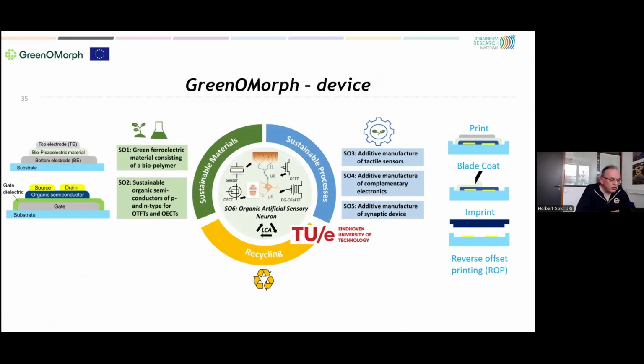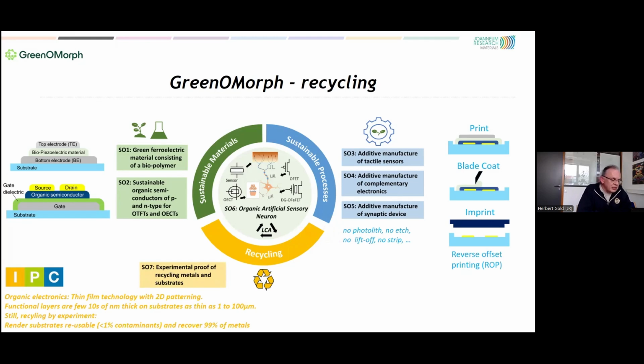So we would create a neuromorphic device by using sustainable materials and additive processes. And it's a layered technology, so we have only tens of nanometers thin layers, and we have substrates which can be as thin as 1 micrometer, but a maximum 100 micrometers thick. Still, we want to demonstrate experimentally that we can recycle the metals and render the substrates reusable. So with only 1% contaminants, and the recovery of the metals our goal is 99%.